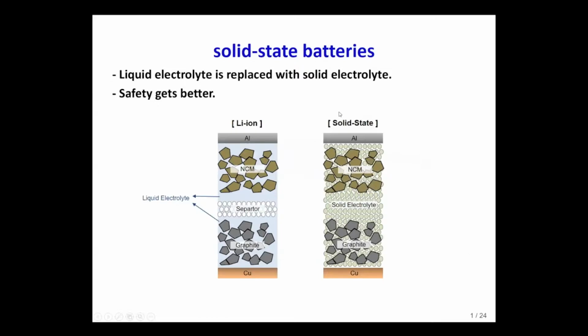Okay, here's a comparison between conventional lithium-ion battery and solid-state battery. We have a cathode and an anode. That is the same, but liquid electrolyte and separator are replaced with solid electrolyte in the case of a solid-state battery. Since we do not have volatile organic electrolyte, the safety will be better. On the other hand, you might need to see that it is very difficult to completely fill the void spaces with solid electrolyte. There are always some grain boundary resistances and also the resistances between solid electrolyte and other components.